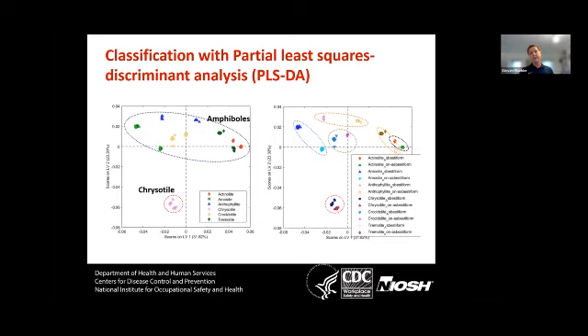So if we have a new size segregated sample, we can put all these fibers on a filter. We can then directly put that filter right into an FTIR instrument, and then we can analyze that and be able to identify whether it's an asbestos fiber, whether it's a non-asbestos fiber, and what the mineral is. And so we've had pretty good success in actually doing that. We're using, again, this partial least squares discriminant analysis. And really what that does is it looks for small differences within the spectra for each of these minerals. And then it can increase those differences to show that we can differentiate between different minerals.